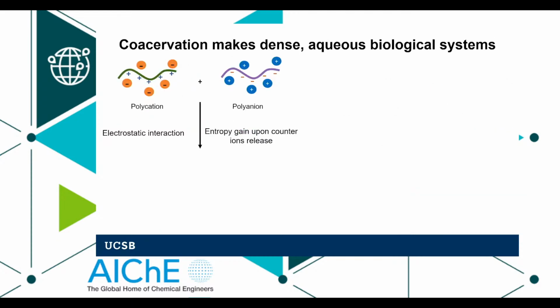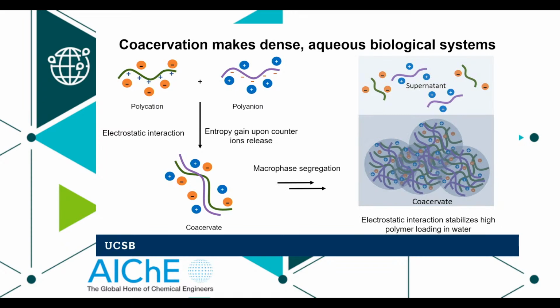So it's at this point that my group started looking around and thinking, can we take inspiration from elsewhere? Biological systems are frequently at very, very high solids loading of big polymers like proteins. And frequently how they do that is using electrostatics to the advantage. Take a polycation and a polyanion. The electrostatic interactions are attractive and pull the chains together, even if the enthalpy of mixing is very, very hard to overcome, right? And you can get some balance. You also get some entropic gain from letting the counterions go, and that's called a coacervate. And these coacervates can be up to 50% solids loading, right, in biological systems, usually in equilibrium with a supernatant phase that's much, much lower concentration.